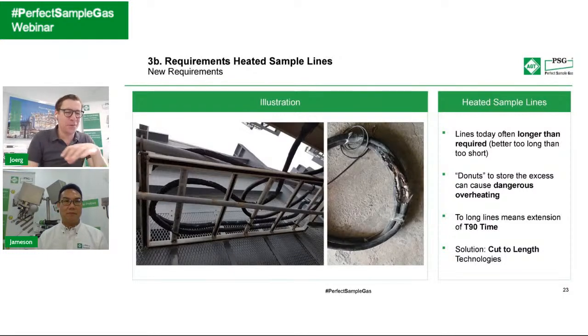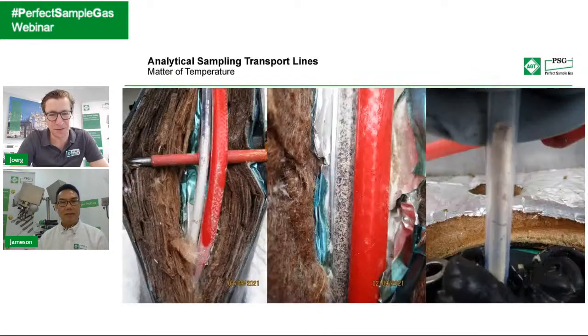So let's pretend you have not chosen the PSG model, which you can cut to length. So you decided to go for the fixed resistant heated sample lines, which you cannot cut to length. But still, if you have a longer length, make sure that there's enough space between the heated lines so that they are not getting too close together. Because as you can see in the picture, this is a real threat, and this is a real problem which can occur there. You accumulate the heat, and then the materials can really even start to burn.